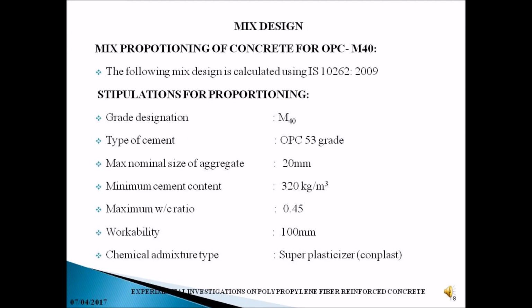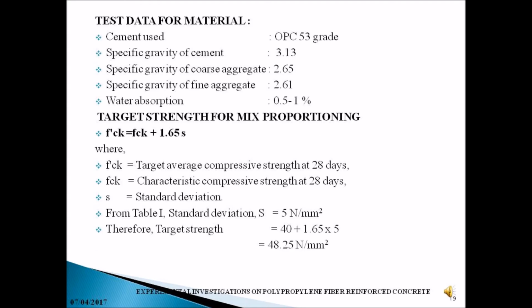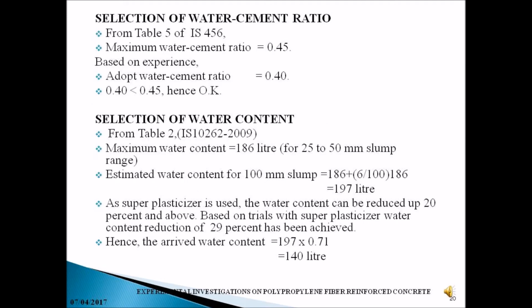Well, coming to mix design, grade of concrete is M40, type of cement is OPC 53 grade. 20 mm is the maximum nominal size of aggregate. Water cement ratio is 0.45. Workability is 100 mm. These are the test data required for the materials. At first we have to calculate the target mean strength. F'ck is equal to fck plus 1.65 S. S is the value of standard deviation.